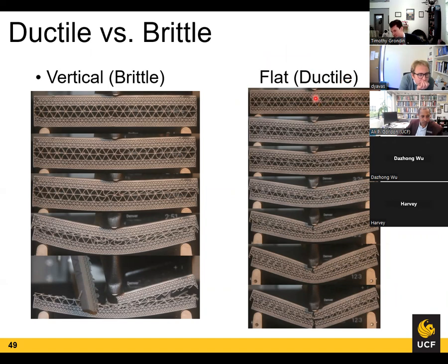So in the flat build orientation, this is really cool. You can actually see the failure in here. You can see the shearing and the direction that these center struts are going. And then we also see that progressive failure in here. So we've got a failure of the center near the neutral axis, and then complete failure at the neutral axis, and then just core collapse right here after the shear stresses, the compressive stresses come in and just crush that.